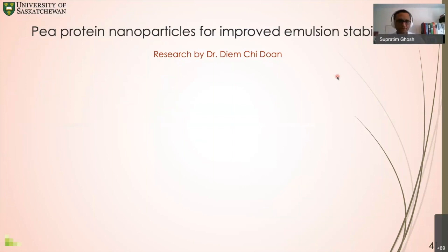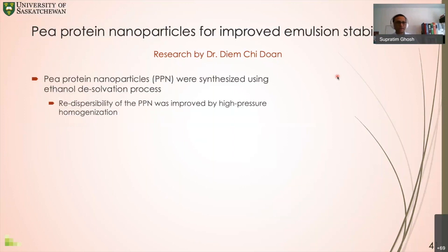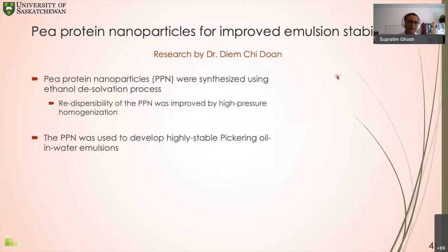Thank you. So what she did is she synthesized pea protein nanoparticles using an ethanol desolvation process. And then she improved the redispersibility of the nanoparticles by again homogenizing the particles, and then used the PPN to develop highly stable Pickering oil in water emulsions.